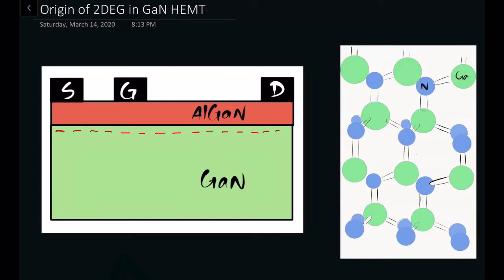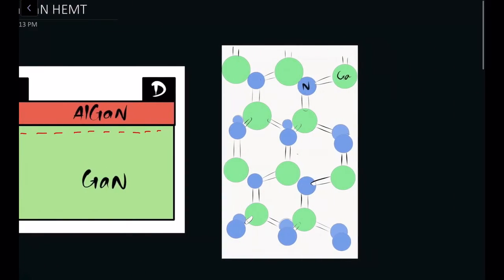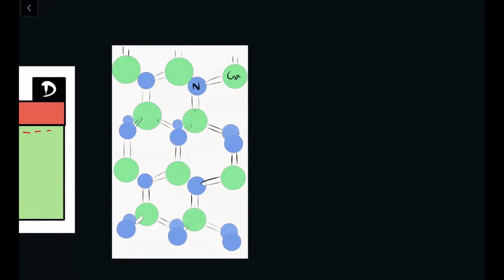Before going into those details, let's have a look at how gallium nitride looks. It has a wurtzite crystal lattice structure. I have already denoted the nitrogen atoms and the gallium atoms, and because of its non-centrosymmetric nature — meaning the atoms surrounding the nitrogen atoms are not symmetric — they are pulling each other, because nitrogen and gallium have different electronegativities. And by electronegativity we mean the tendency of pulling electrons towards an atom. That's why, due to the difference in electronegativities, nitrogen is more negative compared to gallium, and there will be some spontaneous polarization vector created inside the structure.